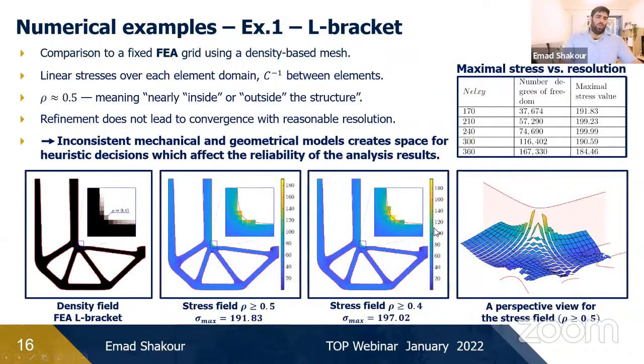Okay, as a comparison, we modeled the optimized design without the stress constraint using a density-based approach. I should emphasize that we didn't compare the optimization procedure, we only compared the analysis on the final optimized design. As we know, in density-based methods, we usually use finite element analysis with C0 continuity between the elements. This leads to C-1 continuity in the stress fields. This means that at the same point, we may have two different values of stresses.